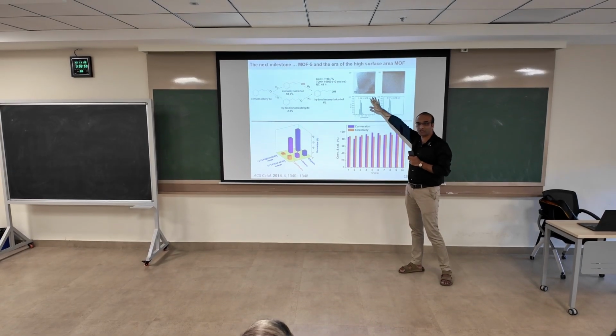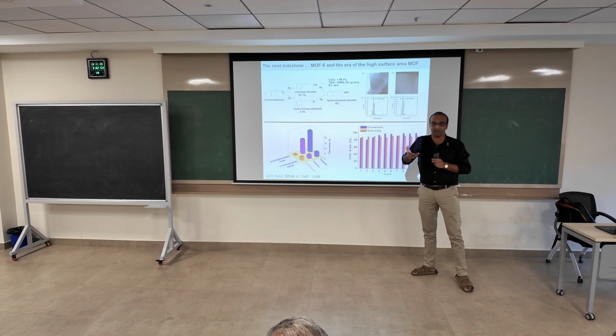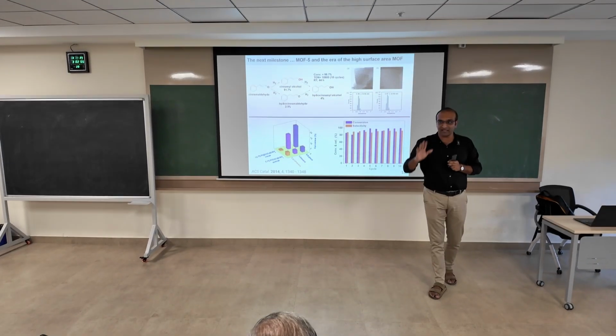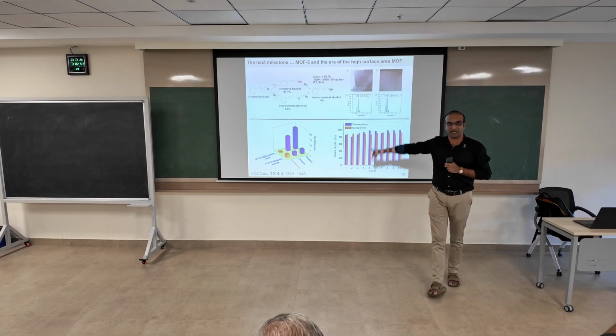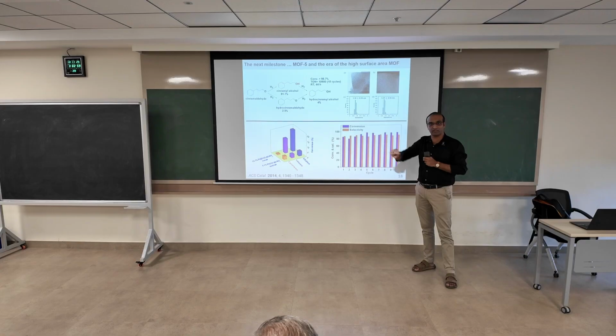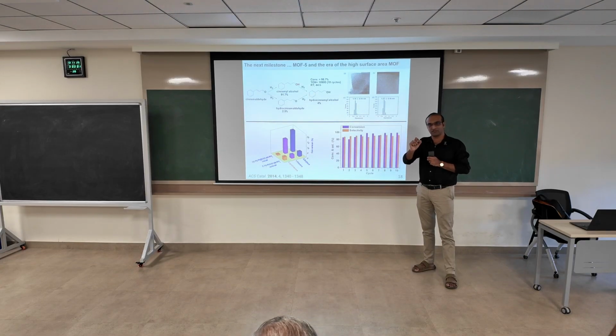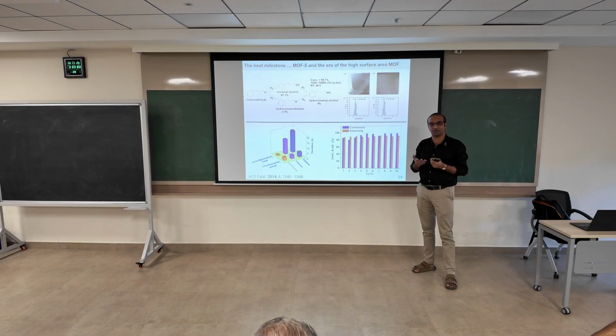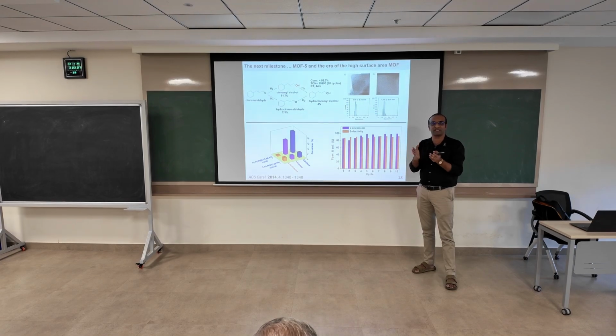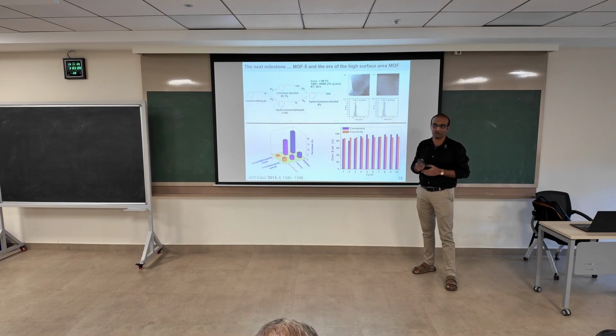But with a typical support that we use in industry, like silica or alumina, which is commonly available, you can probably buy it on Amazon also, if you try to put platinum at a 40% loading, you'll get big particles. When you get big particles, it's of no use because you're basically taking a precious metal and wasting the amount of surface area that's accessible to the substrate, or whatever can be converted into a product.